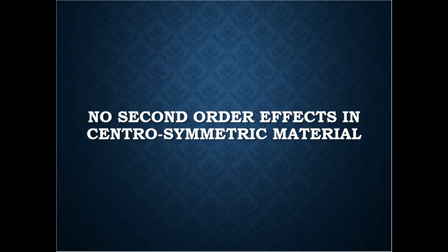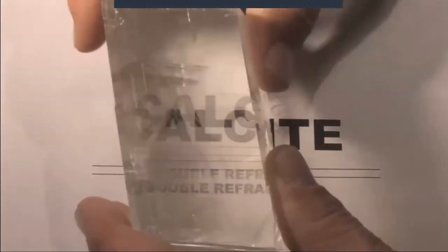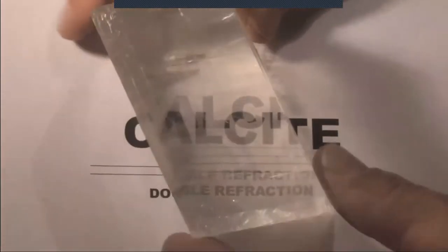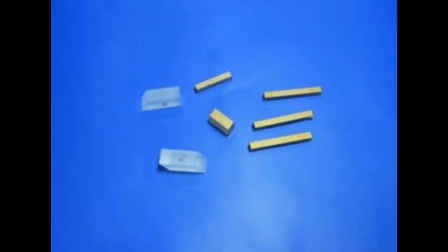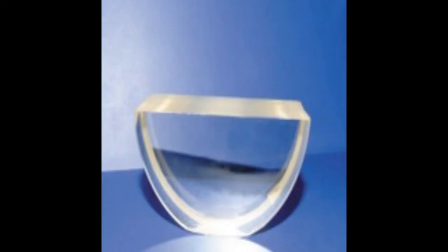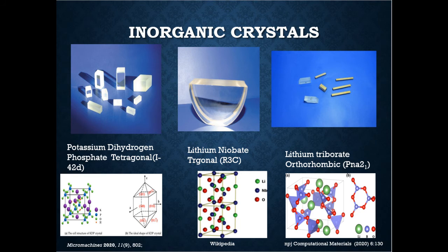In the case of inorganic materials, apart from the non-centrosymmetry criteria, crystals with appropriate birefringence are also a choice. Apart from birefringence, the chosen material must have the required absorption cutoff and damage threshold corresponding to the input laser power. Historically, quartz crystal was the first material used in the demonstration of the second harmonic generation of light with ruby lasers. Subsequently, many systems like perovskites, tungsten bronze type materials, iodates, phosphates, and nitrates have also shown nonlinear effects.